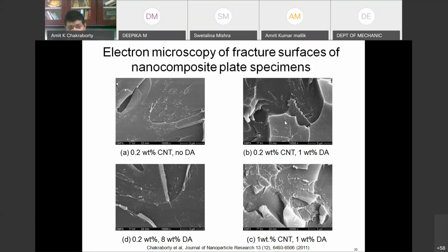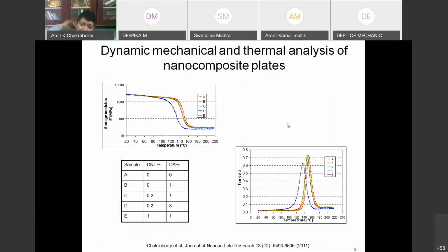There are no large, long CNT particles. CNTs were long particles, long hairs, right? But here in the fracture surface, we do not see many long hairs. The reason is that during the mixing process, we have also cut down the long hairs into very small particles. So the impact of fiber reinforcement has also been compromised. The fibers are no more fibers; they have been cut into smaller fiber-like particles, and that is also a problem which did not help in stopping the crack propagation or fiber pulling out.